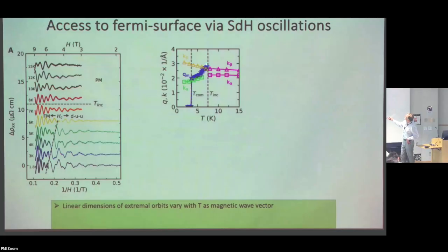So what we measure in diffraction is these blue points, and what we see from Shubnikov-de Haas is that the linear dimensions of the Fermi surface are changing with a slope, let's say dq/dT, which is similar to the magnetic wave vector. So this is a fairly mild connection that we're making between these two, but at least they're not orders of magnitude off. And so what I'm saying is that from this we can take a hypothesis that this change in the wave vector with temperature of the magnetic structure is actually driven by modifications in the nesting conditions on the Fermi surface. That's what we draw from that.